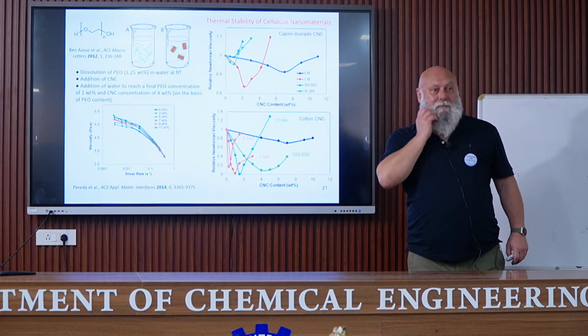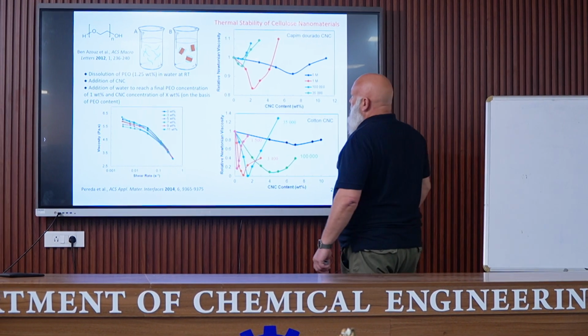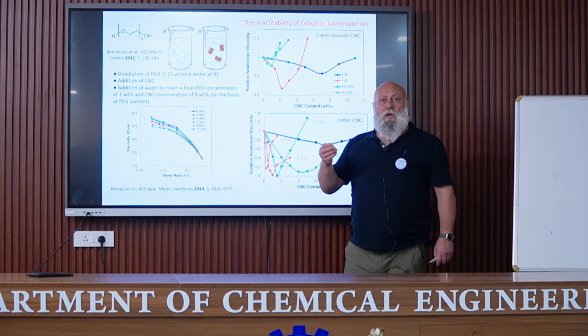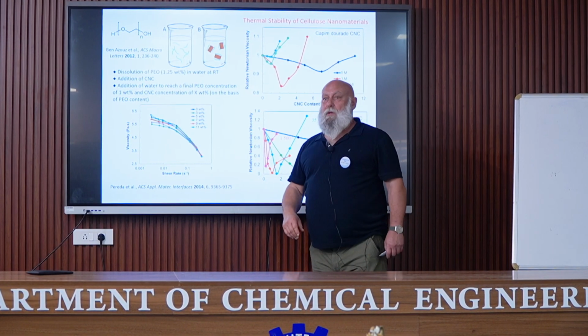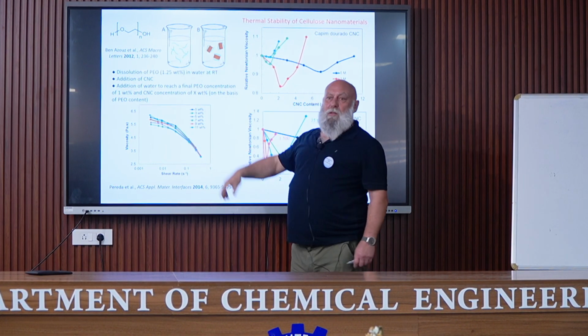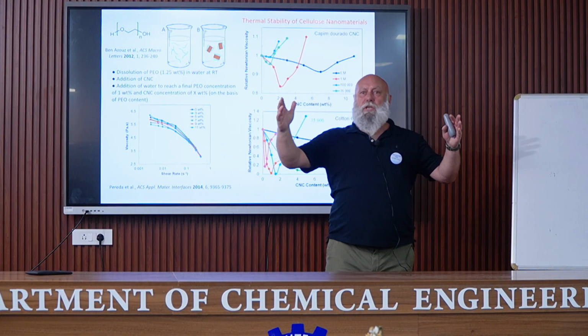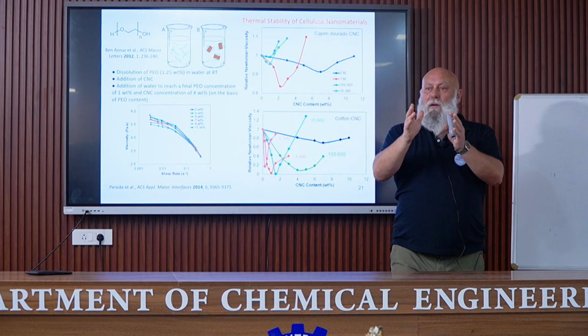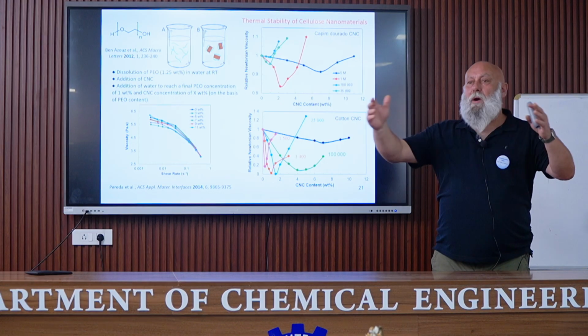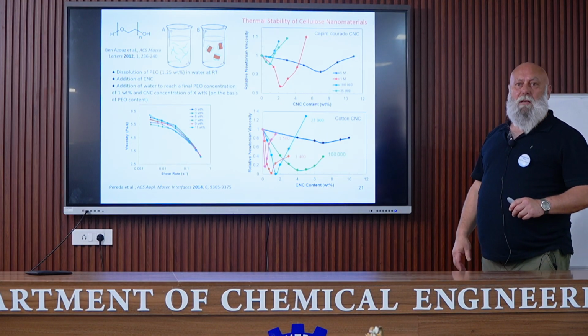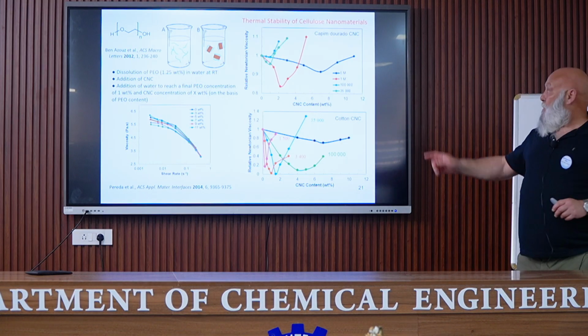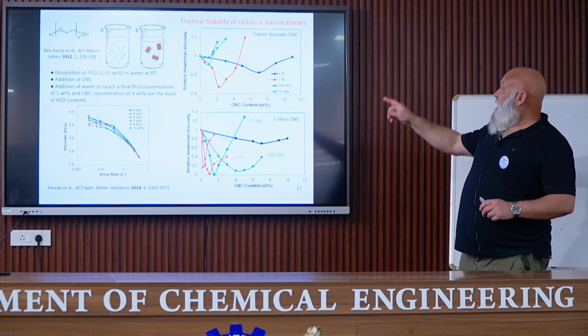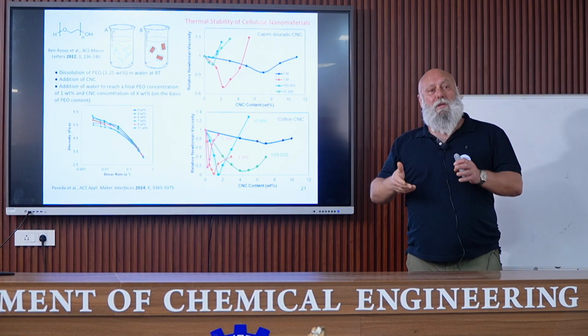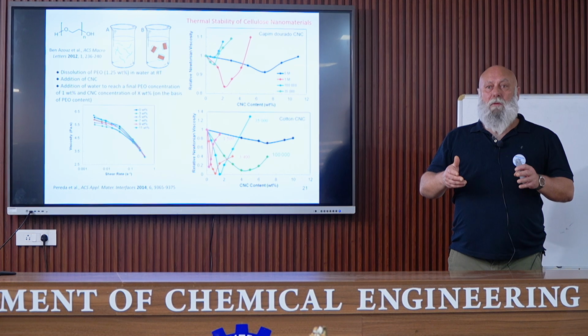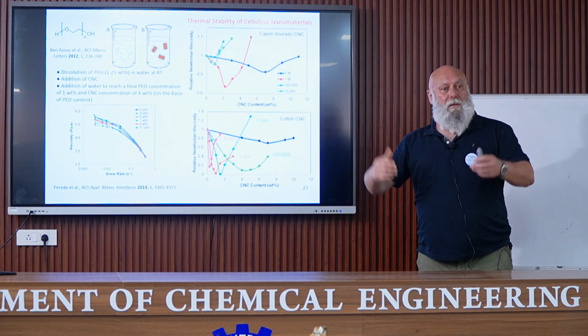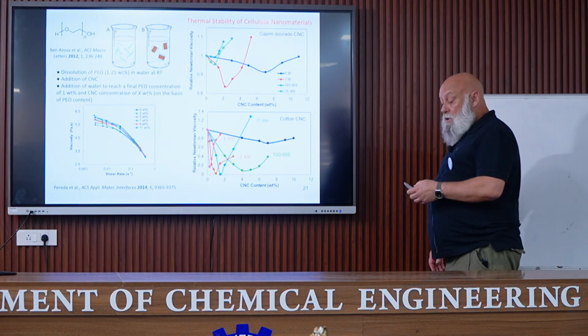So what happened? Most probably, there is a good affinity, of course, between polyethylene oxide and the surface of cellulose nanocrystals. When adding the cellulose nanocrystals, the PEO chains tend to go to the surface of the nanocrystals, meaning that there are fewer polyethylene oxide chains in the solution. It results in a decrease in the viscosity. And then, when the surface of the nanocrystals is completely covered, of course, we have an increase in the viscosity of the suspension.